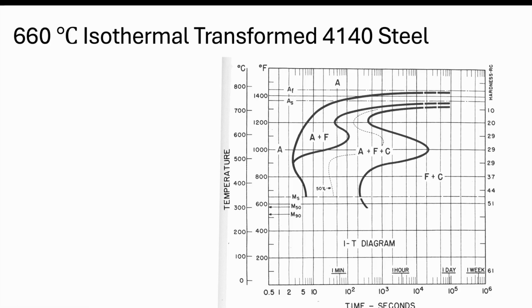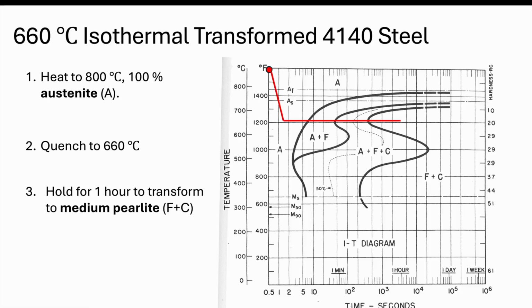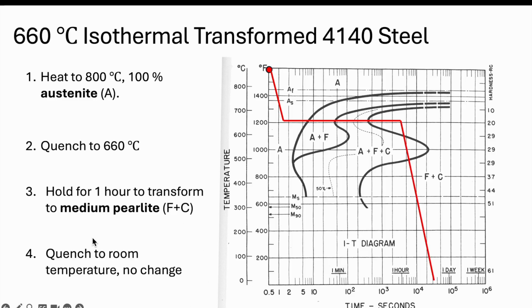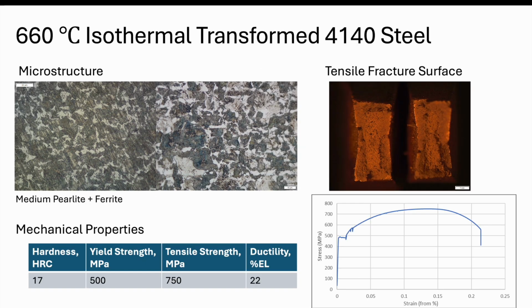All right, so 660. In this case, again, this is where we would expect to see the medium perlite in this structure, and let's see what we actually get. So 660, again, we expect to see medium perlite and ferrite. So again, the light regions that you see in both these micrographs are ferrite, and the darker regions, where you can see some of the layering in these various regions, that layering is our medium perlite. So the layers are a little thicker than the previous sample.